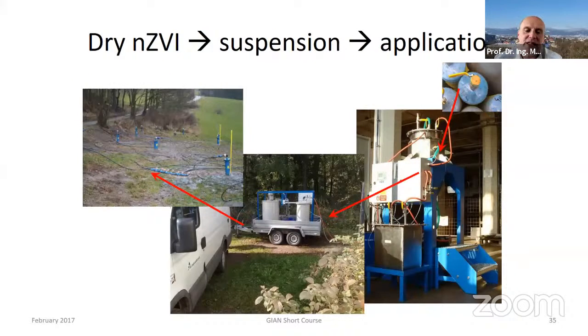This is how it looks in reality, in full scale, because we apply this method in many sites, not only in Czech Republic, but also in other sites in Europe. If you go from the right side, you see the tank with the reactive particles. You mix them on the side to make some suspension. There you also add some surfactant to make them less reactive, but more transportable.